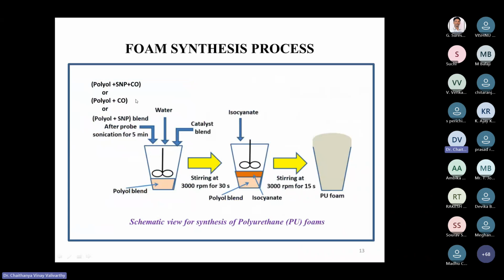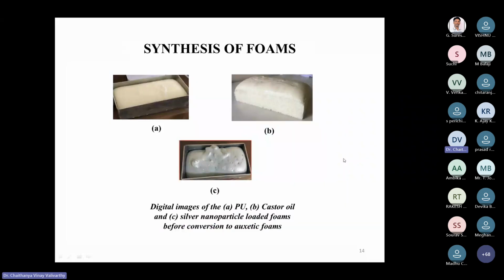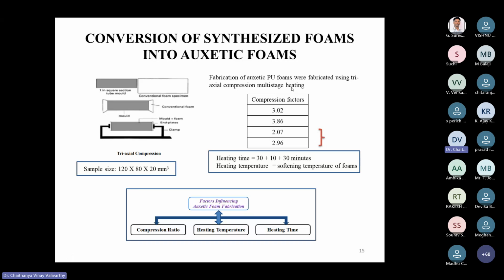Initially, I added polyol and SNP plus castor oil, and then sonication for 5 minutes, and then we added water and then catalyst blend, and we stirred at 3000 RPM for 30 seconds, and then we add the isocyanate, and then we stir at 3000 RPM for 15 seconds, and then the PU foam forms. The shape of the PU foam is completely based on the shape of the container. So these are the foams. We have this layer. We are just taking the middle part of the foam. We are not taking the surface part of the foam. So now we have made these PU foams. We want to convert these PU foams into auxetic foams.